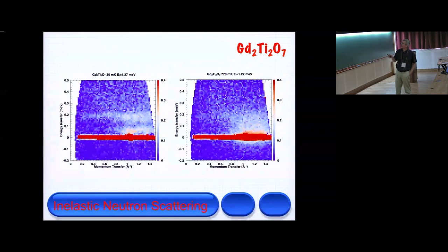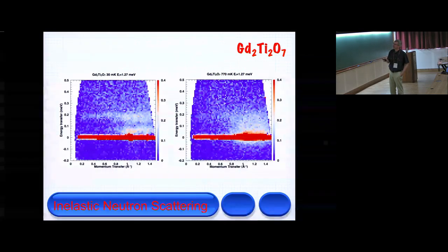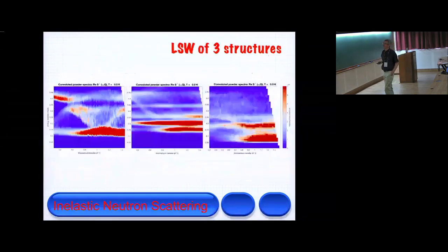That's obviously, this is at 770 millikelvin. It's temperature dependent, which is a sign that it's probably magnetic. And then there's this flat band here. Maybe it's flat, you can't say much. This is powder averaged in a small sample, but it's also broader here, so maybe there's some dispersion down here, maybe there's 2 bands. In this intermediate phase, the spectra is definitely very different.